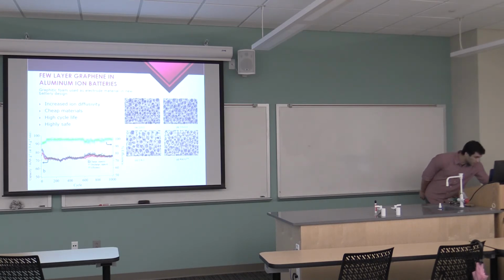You can see, oh yeah, okay, so this graph on the bottom left is showing you the current capacity over the range of cycles, and you can see that the discharge current, which is the red, or discharge capacity, and the black squares, which is the charge capacity, remains pretty constant over the course of 1,000 cycles. And the efficiency, which is that top green line there, stayed pretty much flat across those 1,000 cycles, which is a good indicator that obviously there was no loss in capacity.